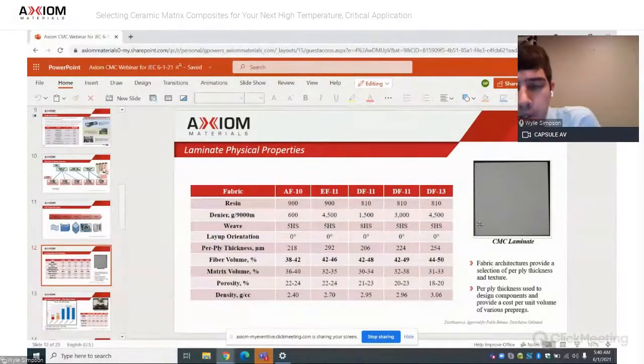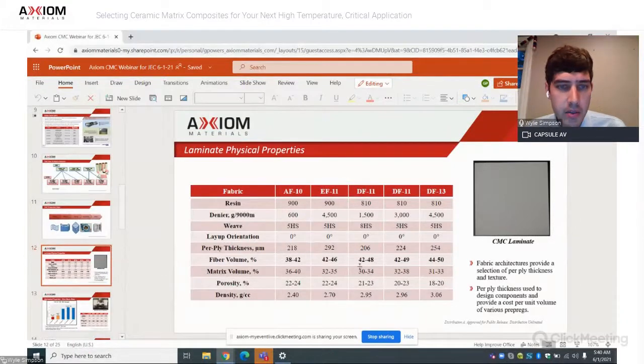So here's some of the typical properties we see from our CMC prepreg. The naming system up here, AF is the 312 material. EF, if it starts with an E, that's the 720 material, the highest temp grade material, and then DF, that's the 610 grade stuff. And they offer a bunch of different fabric architectures and different weave styles. So different deniers, different weaves, and that allows you to sort of tailor your per ply thickness for your design, end of life design component. So there's a various degree of per ply thicknesses that we offer. Seen here, the higher the number up here, typically the higher the per ply thickness.